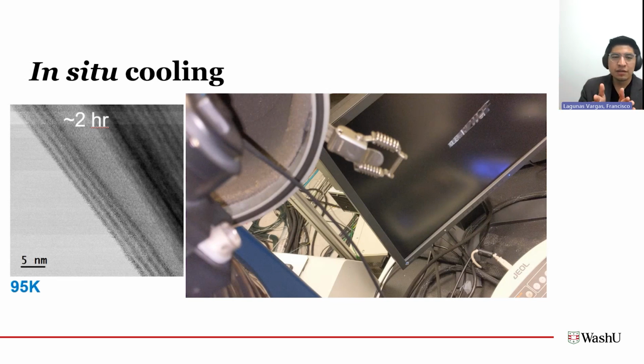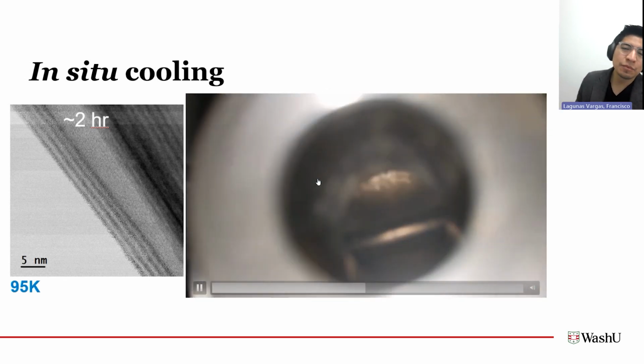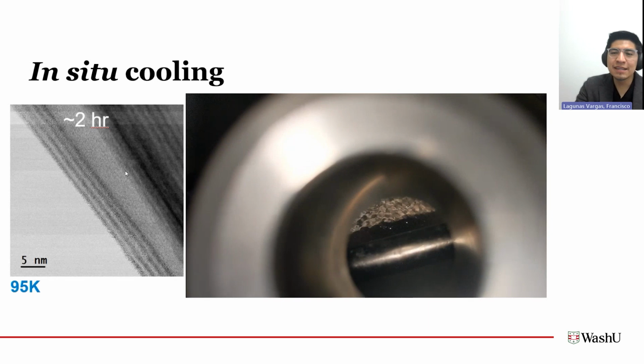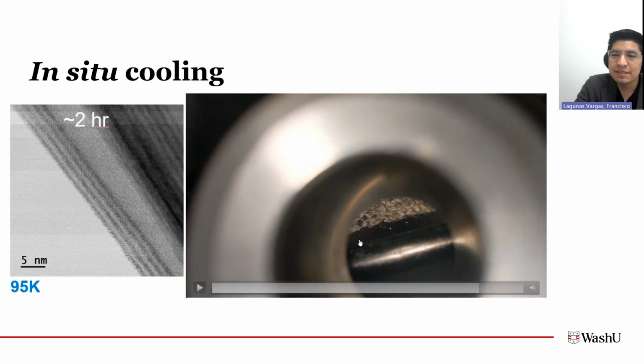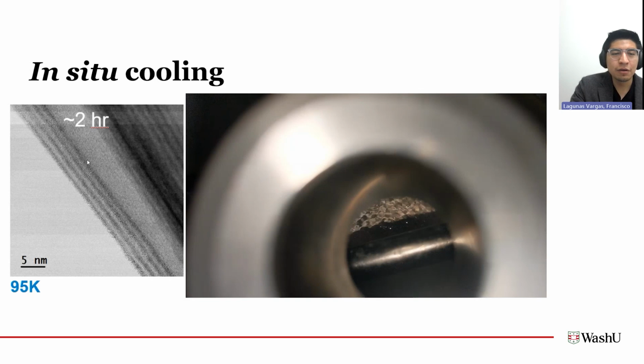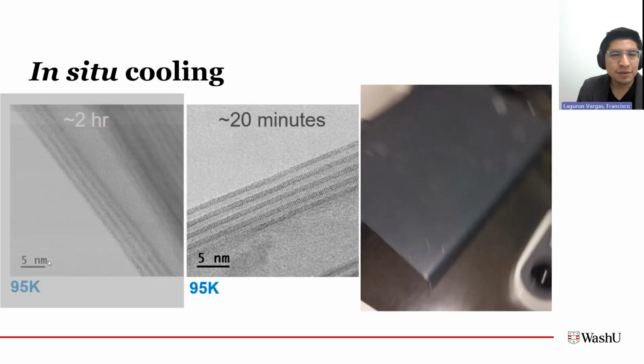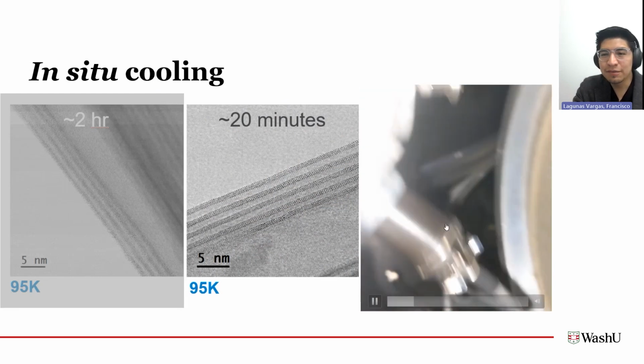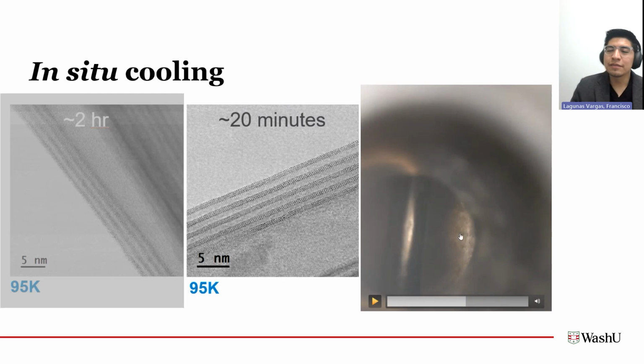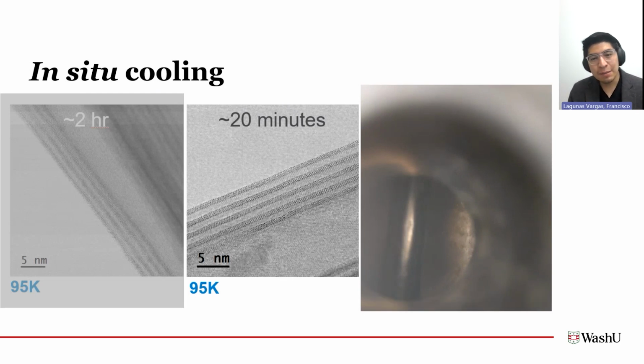And then even once the holder itself has reached some sort of thermal equilibrium, you have a pot of liquid nitrogen that is slowly boiling away. And this boiling will introduce a lot of vibration into your imaging. So I have an image here that I acquired when the sample was stable. And you can see this is the state of the dewar when I acquired this image. You can see this liquid nitrogen boiling away. And that's what's introducing all of the vibration that makes acquiring high quality STEM images very challenging. What you need to do instead is wait for the dewar to be just low enough that there's still liquid nitrogen in there that can keep your sample cool, but not enough that the vibrations that come from this nitrogen boiling away are impeding your imaging quality.